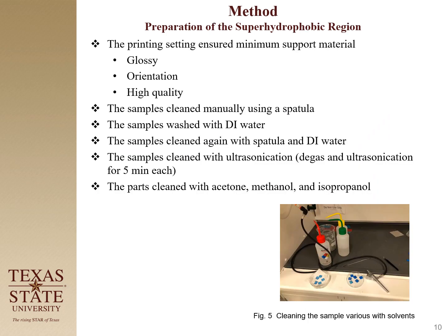After printing my sheets, I cleaned them manually, and also with sonication, to make sure that there is no support material from the printing on my sheet, also by using solvents. I use acetone, methanol, and isopropanol to clean my samples.